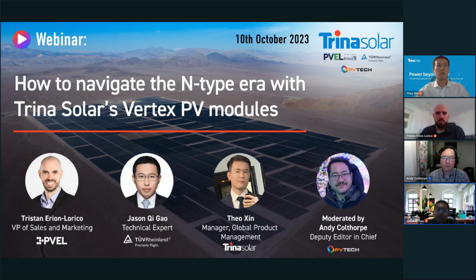The rated power before light soaking is the power just after the production line, and the rated power after the light soaking is actually the real power in the field. So although metastability was found in the measurement of the HJT module, the HJT module is actually not so sensitive to metastability, since we can only see the complicated metastability behavior after 5 to 10 hours of light soaking.